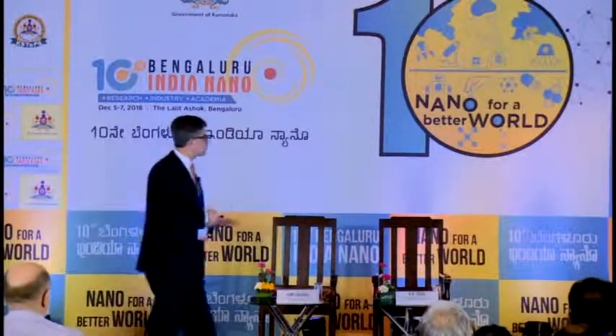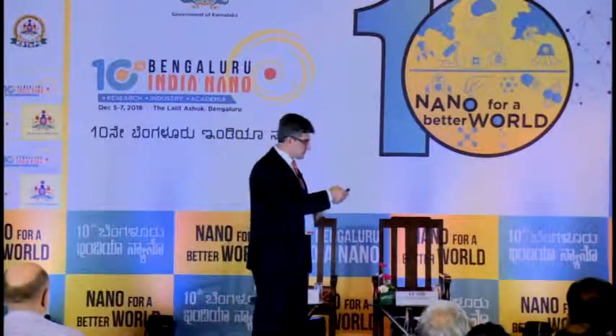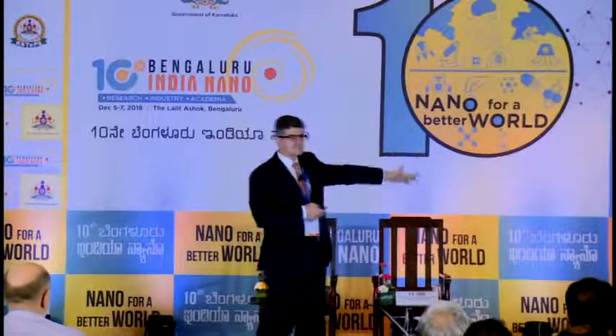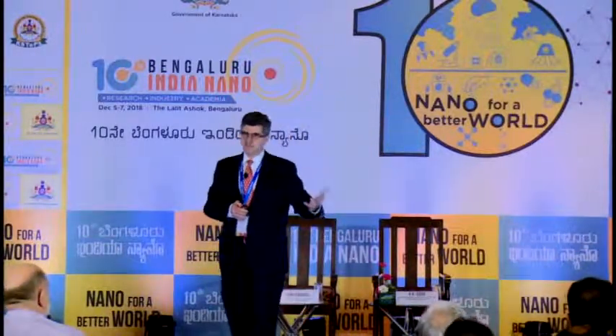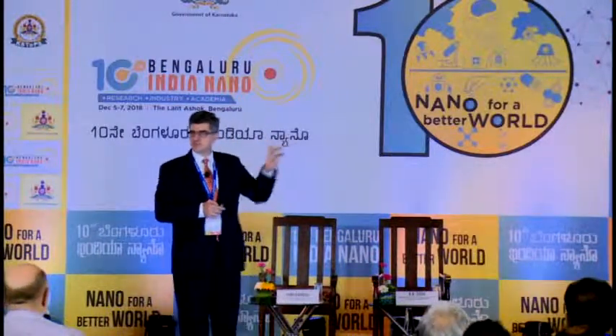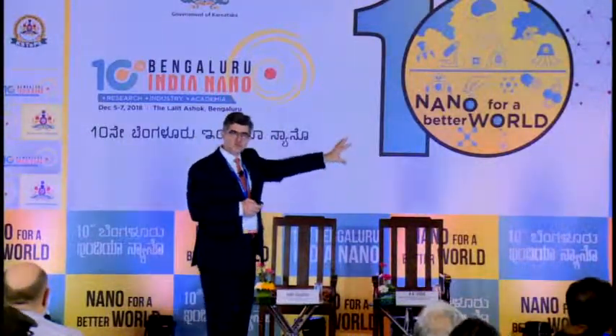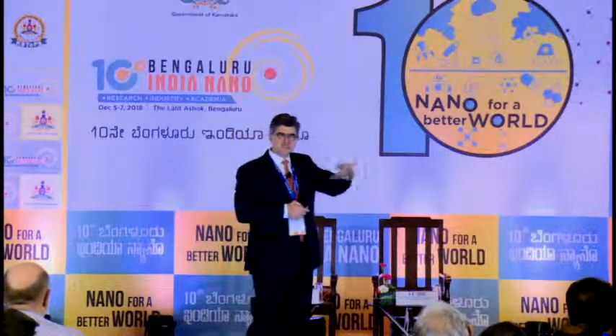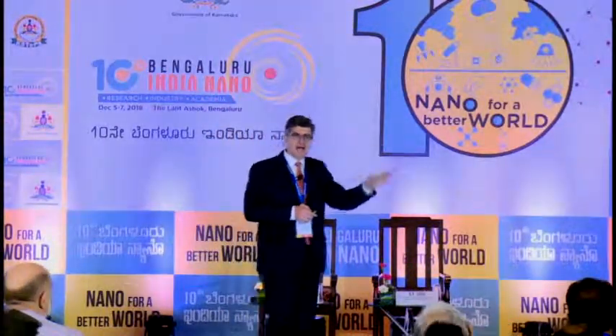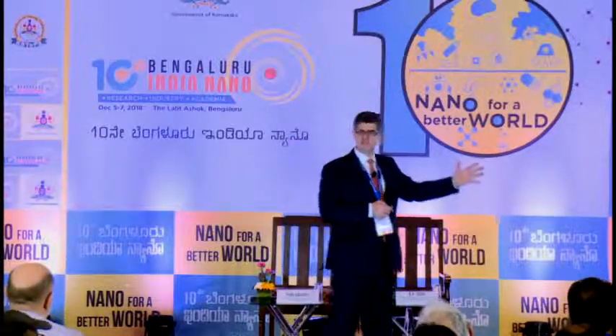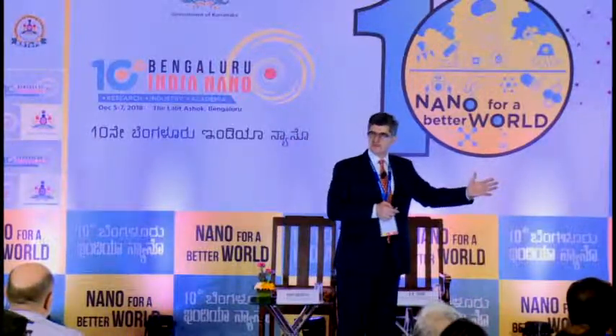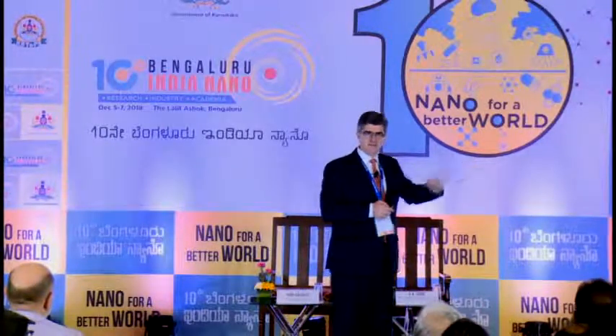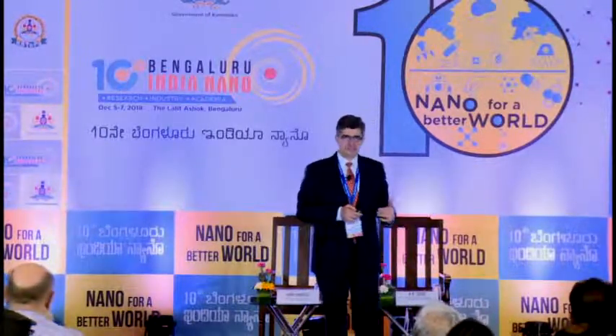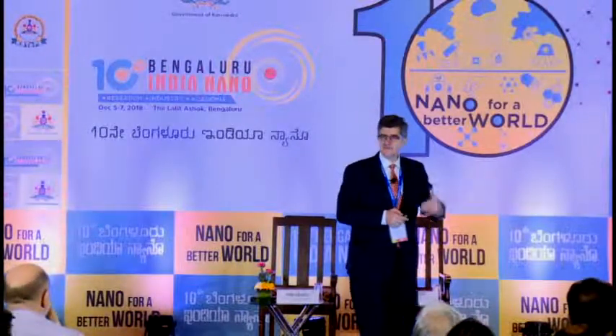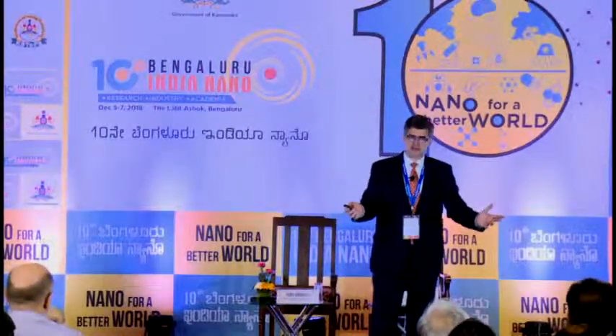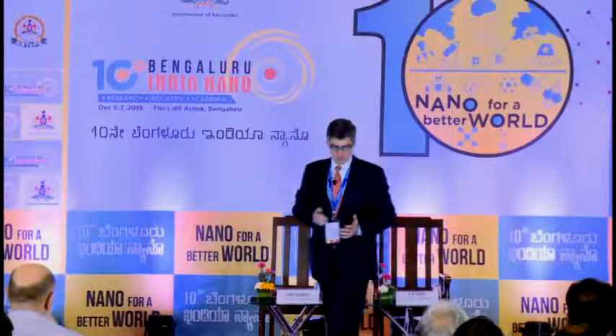And of course, depending on how we do the synthesis, we can produce materials which are quite perfect crystals. You can see even a hexagonal symmetry inherited from the precursor phase. And we can make materials with a lot of pinholes. And it doesn't necessarily mean one is bad, another is good. If you want to have high surface area, if you want ions to easily diffuse through the layers, we want to have defects and pinholes. If you want to have a very strong coating with tens of gigapascal tensile strengths, if you want to have extreme conductivity, we want large and perfect particles. It's all about being able to control it here.